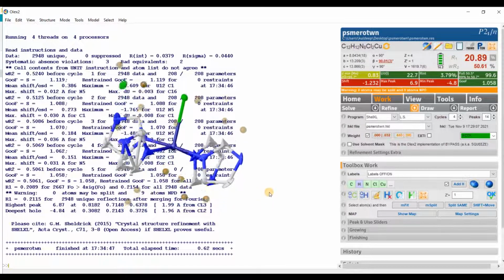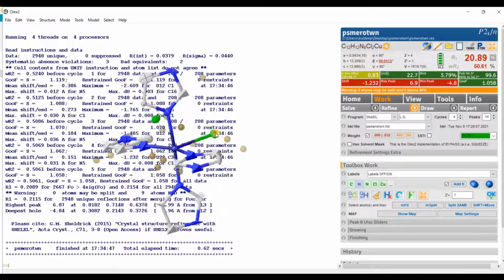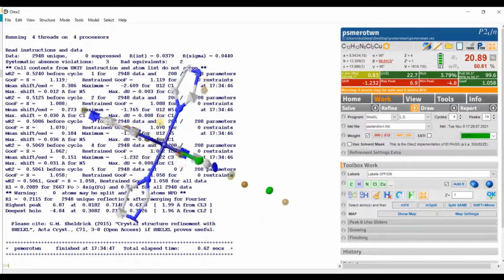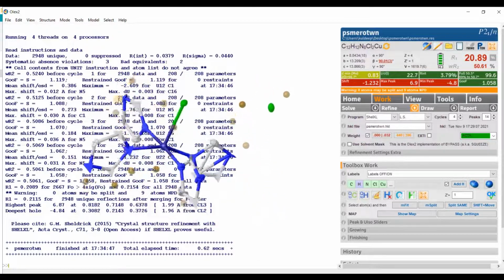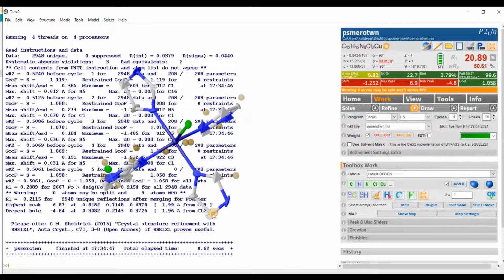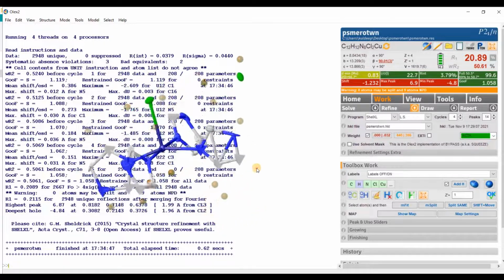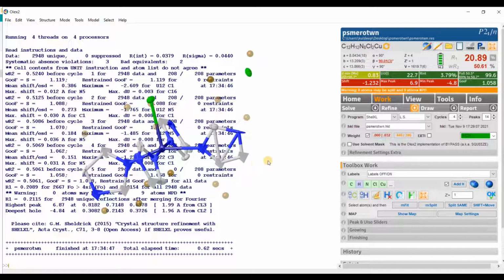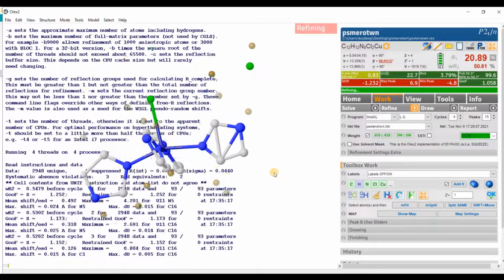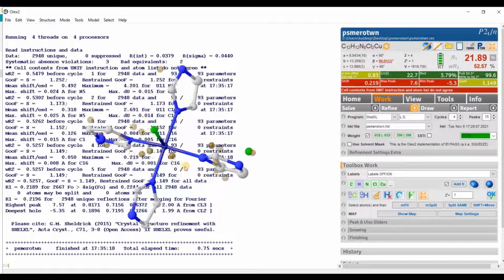Now you can see the R factor is not improving, but some atoms become triangular in shape, because they are non-positive definite. So the anisotropic refinement will not work here. So we have to go for the twinning. Okay, so first I will set back to the isotropic refinement. Okay, so now it's looking somewhat better.